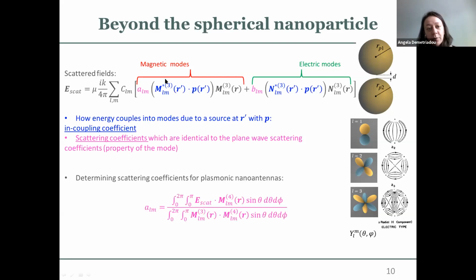And to obtain these scattering coefficients, you can do it 2 ways. You can apply your boundary conditions and obtain them, but that's pretty difficult because the system explodes in the gap. You have too many wave functions there. Another way is to calculate them numerically and then fit them in this formula, which will allow you to find the scattering coefficient for a given L and M. And you can do a similar thing for the other scattering coefficient.